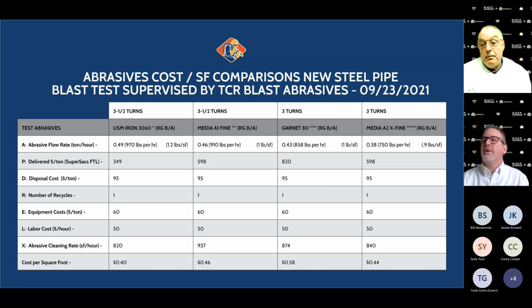Well, that's a great way to look at it, Keith, and a very quantitative way to look at this. If I may, too, Edith is asking on the profile. So the mil profile was anywhere from 1.5 mils to 2.5, almost 3 mils profile, just depending on the material. The finer materials, the ones that we had the 3 turns on, had the finer or the lower profiles. And again, the type and size of nozzle was, as mentioned before, a number 6 nozzle. And the type is a standard single Venturi nozzle.